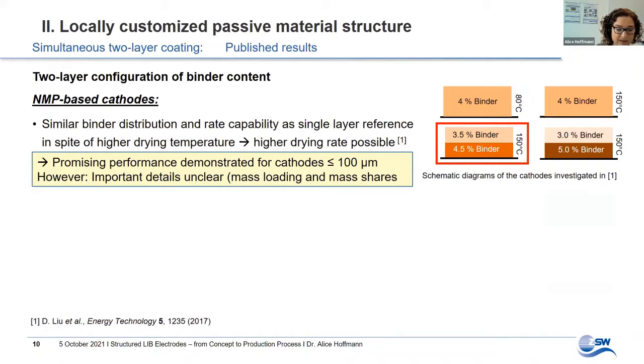There are already results about simultaneous two-layer coating reported in literature. For example, in a study of Liu, single and two-layer cathodes have been prepared with varied binder content and have been dried at low and high rates. And a two-layered cathode showed similar binder distribution and rate capability as a single-layer reference, although a higher drying temperature had been applied. High drying rates are principally desirable because they enable cost reduction. So a promising performance was shown for cathodes thinner than 100 micrometer.